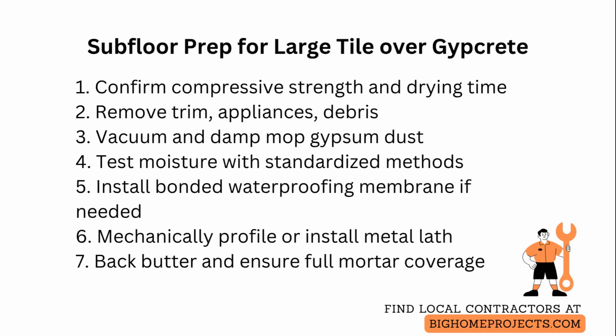Test moisture with a calcium chloride test or a relative humidity test and compare to the thinset or membrane manufacturer recommendation, because gypsum will absorb and release moisture differently than Portland cement. If moisture is above the limit, delay work and use a proper vapor control strategy, such as a bonded waterproofing membrane designed for gypsum underlayments, applied after profiling the surface.